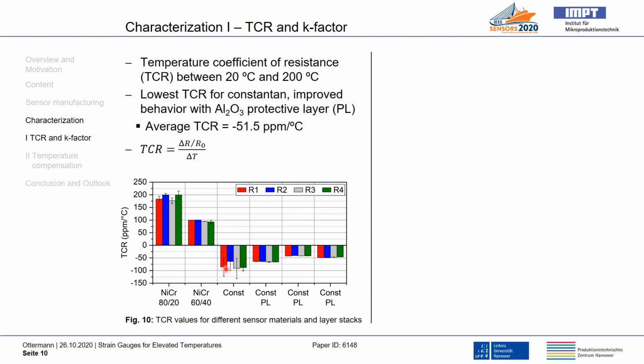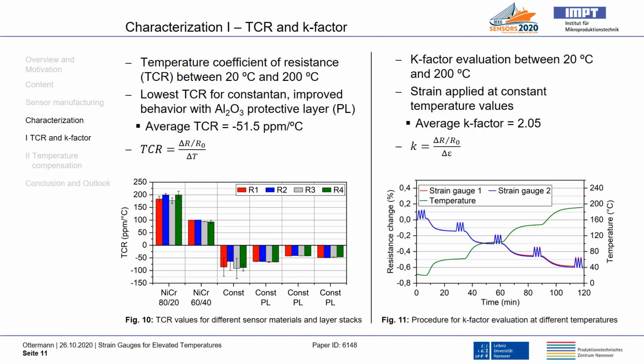In order to minimize these deviations, a protective layer out of alumina was added. The result is an average TCR of minus 51.5 parts per million per degree Celsius. With this evaluated layer stack, the K-factor measurement up to 200 degrees Celsius takes place in a tensile test stand.